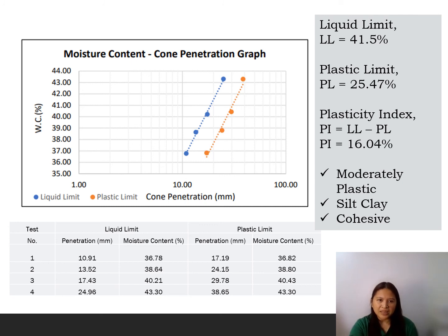So the liquid limit and plastic limit are determined from the resulting graph of the moisture content versus cone penetration depth. From our plot, we therefore have a liquid limit equal to 41.5%, plastic limit equal to 25.47%, and so the plasticity index, the difference of the two, is equal to 16.04%. So these values tell us that the soil is moderately plastic, so its composition is silt and clay, and it is cohesive.